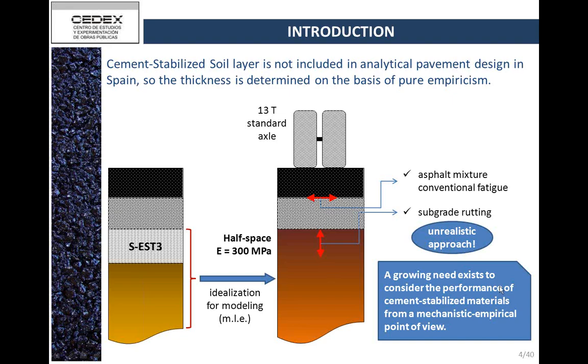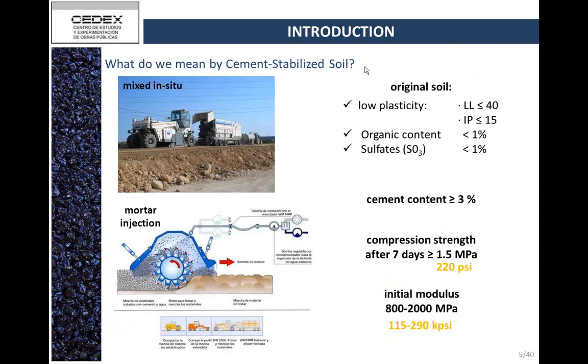But there is a growing need to consider the performance of cement-stabilized materials from a mechanistic-empirical point of view. The first thing is, what do we mean by cement-stabilized soil? Because I see that different countries have different names for similar materials, or maybe the same name for different materials. When we say cement-stabilized soil, we mean that we typically use a medium-high quality soil. The soil can have some plasticity, like you can see here, a plasticity index below 15. You can have some organic content, sulfates, but it's not a very bad soil for sure. And the amount of cement is typically over 3%. In fact, the norm requires that the minimum content of cement should be 3%.